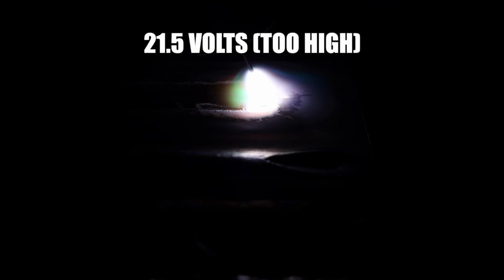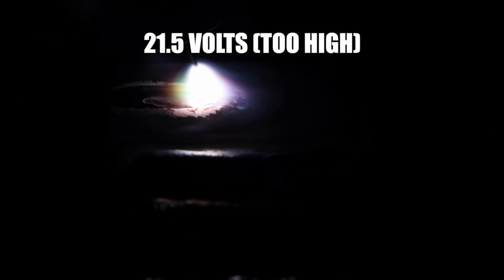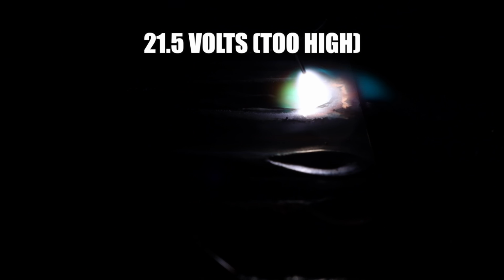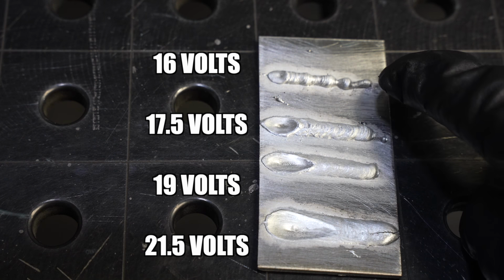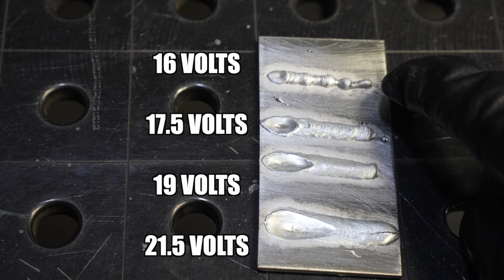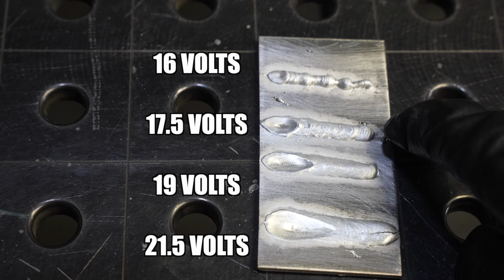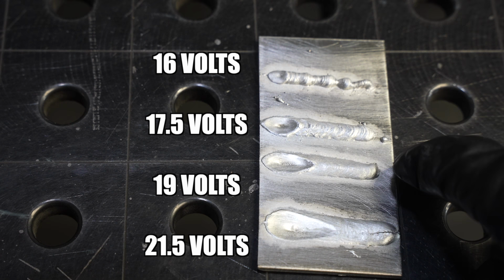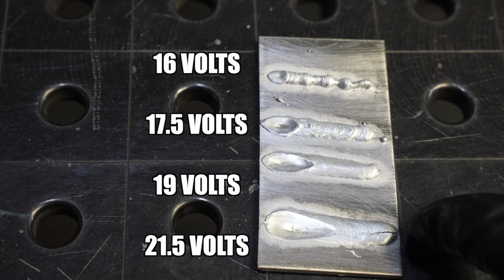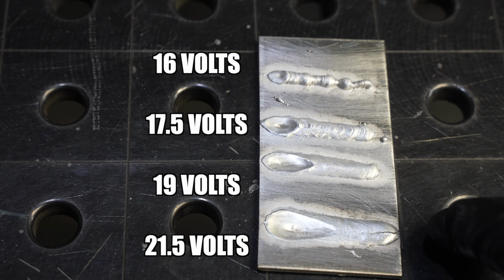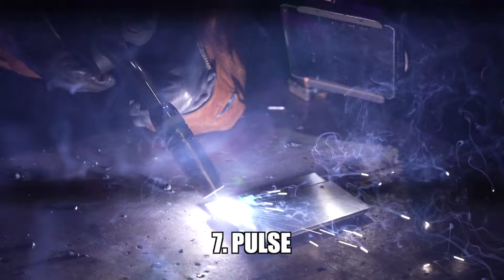But if my voltage goes too high, that arc length gets really long and it's hard to control. It could just be too much heat and spread your weld out too much. So if you look through here, you can see the result. Definitely a big difference as I increase that voltage, and I'm looking for a sweet spot just like that right there that ended up on 19 in this case. But if you just go through this Goldilocks type experiment, you can find the exact spot that you need.